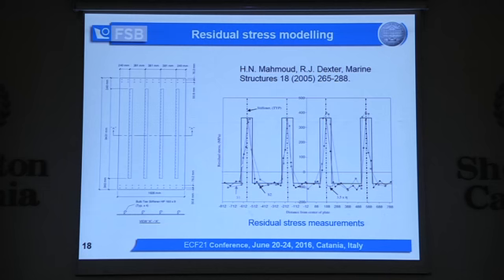So, and you have stresses which reach tensile yield strength here at this part. So this is, for example, 1/4 is under tension and 3/4 is under compression. And so we assume that in our model this residual stress distribution, because it should be idealized, it's more or less random, but it's always like this. And I want to point out that real distribution is between rectangular here and triangular.